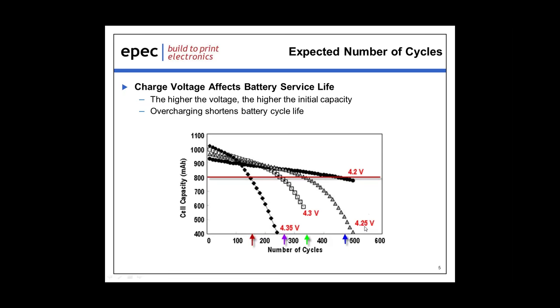At 4.25 volts, only 50 millivolts overcharge, which is very very small. Here, normally your 4.2 volts, you're going to get roughly 500, a little less than 500 cycles per this chart. At 4.25, if you fall down to the green arrow, you just drop a lot of 100 cycles. That's like over 20 percent capacity loss just on 50 millivolts overcharge. So what's really important here is to understand the charging system you're using. Make sure it is very accurate on voltage regulation. We normally want to stay within about 1 percent on charge voltage. Current doesn't need to be that accurate. We current limit, but we voltage regulate in order to make sure that we don't suffer from cycle loss inadvertently just from a poor design in battery charging. And obviously you can see from this graph that it gets even worse. If you get down to 4.35 volts, just 150 millivolts overcharge, you're going from about 500 cycles down to 150. It just kills your battery.